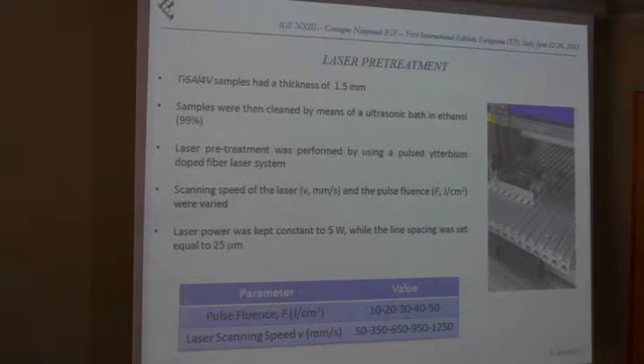So the first step is, of course, the laser pretreatment. As I reported in the slide, we cut out of a sheet which was 1.5 millimeter thick our samples by cold blanking, and then we cleaned the samples under ultrasonic bath in ethanol, and we treated the sample. In order to reduce the number of experiments and to focus into two different parameters that we could change over the laser, we fixed the power constant at 5 watt, and also the line spacing to 25 microns, which is also the spot diameter according to the lens that we were using.